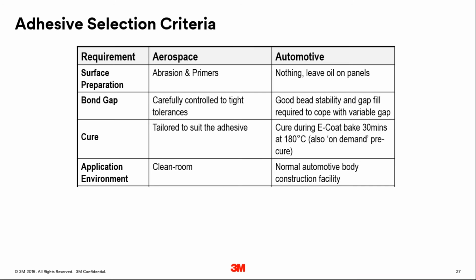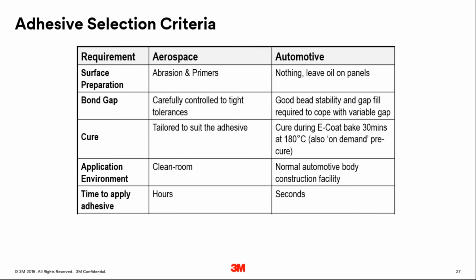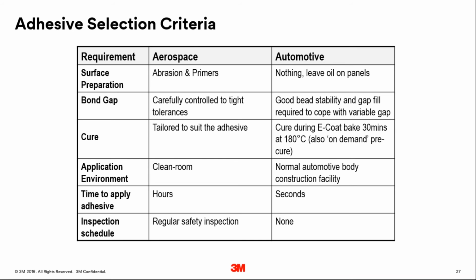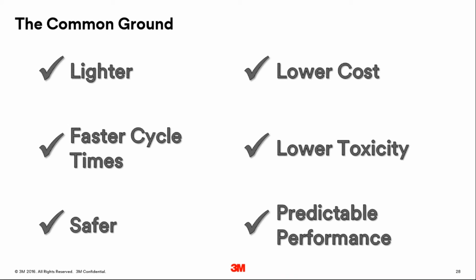And we have much more time to apply our adhesive in aerospace, again achieving that controlled bond line and ultimate performance. Whereas automotive will only give us seconds to apply the adhesive. And in terms of an inspection schedule, thankfully we have a regular safety inspection schedule in aerospace, whereas in automotive it's left in the hands of the final customer. But it's not all about differences. There's an awful lot of common ground. Both industries want to produce lighter structures at a lower cost, and faster cycle times are needed to hit the production volumes. Also looking for lower toxicity and safer structures with more predictable performance as CAE becomes the mainstream.